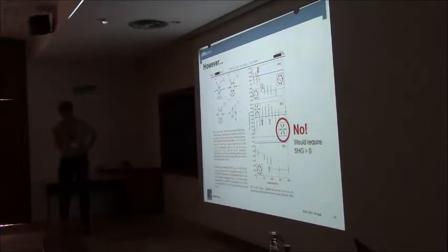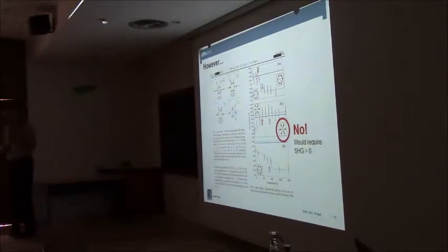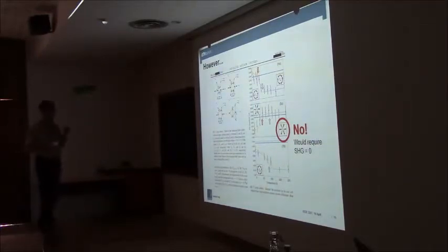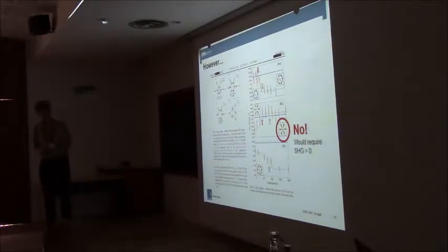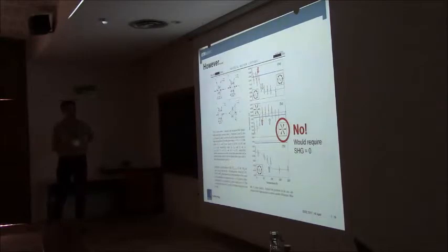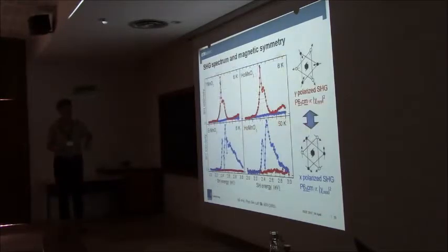And nevertheless, because it's this rather strange technique to determine structures optically, frequently there are papers in the literature claiming other structures, all spins out. It's not possible. It would require second harmonic generation being 0, this structure. But we see second harmonic generation. Their criterion is, with a large error bar, a certain position of the manganese ion. So is it a little bit below 1/3 or a little bit up? So it's a really fine measurement from which they conclude this. And here it's simple. It's, do you have a signal or don't you have a signal?